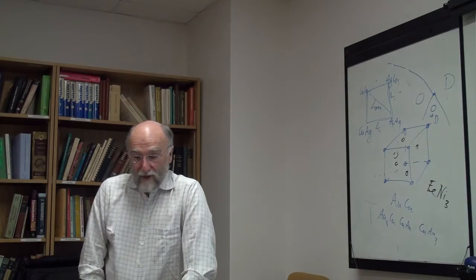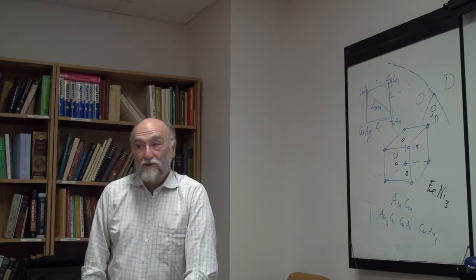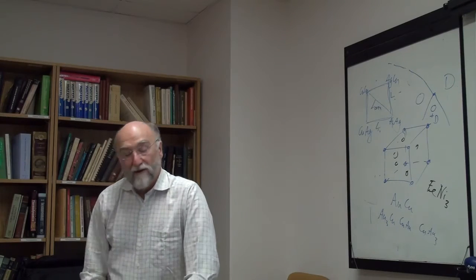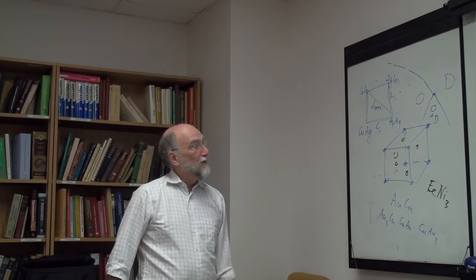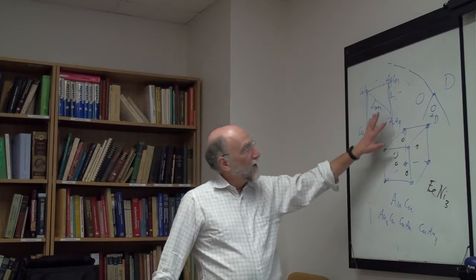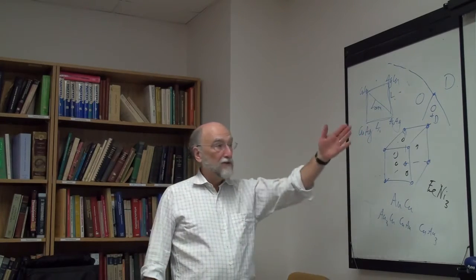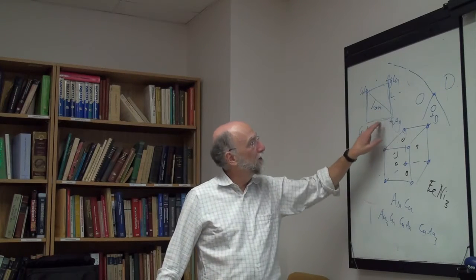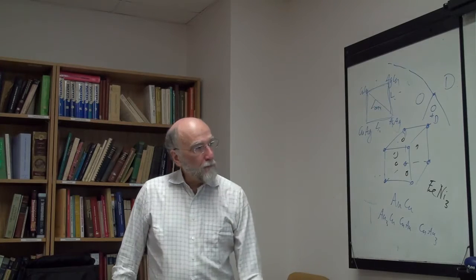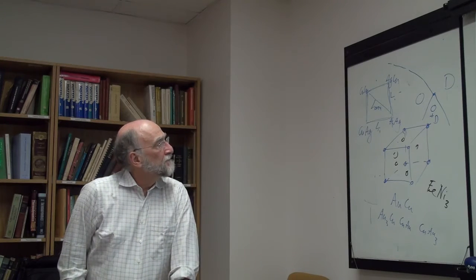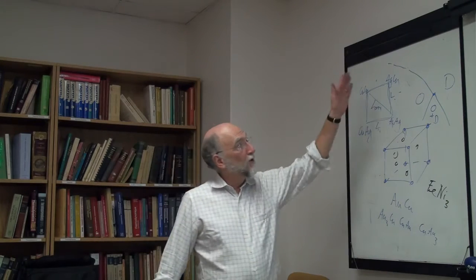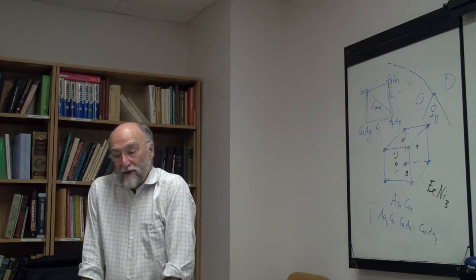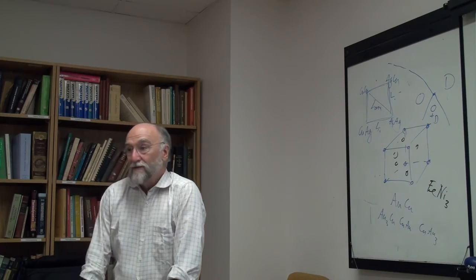Okay, but I don't pretend to be an expert on order-disorder transformation modeling. Anyway, to do it with the compound energy formalism in a simple model in order to predict the overall, you can predict the tricritical points too. They're easy to do with the compound energy formalism. You have to put in an L1-2 term here. But that's not too terribly difficult. But in order to fit quantitatively, to do an optimization with the order-disorder, it becomes very, very complex.